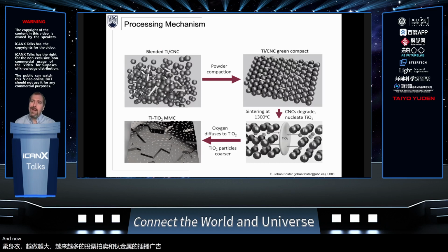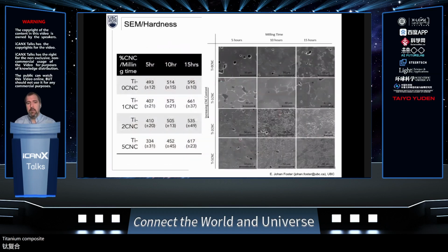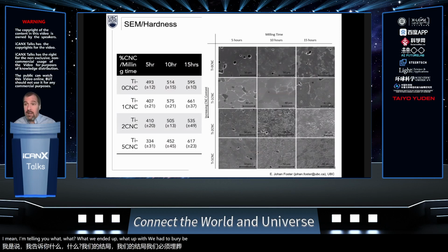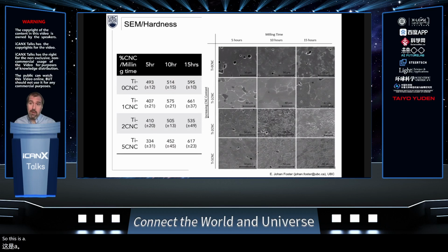And now you've got a titanium oxide, which is a ceramic, reinforced titanium composite. Okay, so I'm telling you what we ended up with. We had to vary the amount of milling time, prior to the sintering, the milling time of our cellulose nanocrystals with our titanium. Vary the amount of cellulose nanocrystals in this.